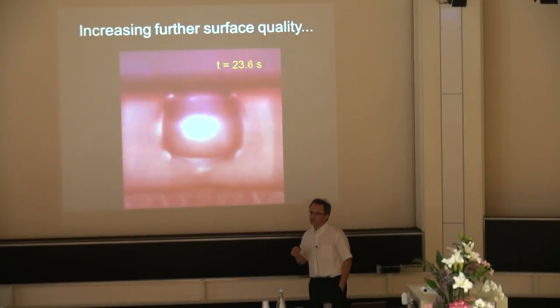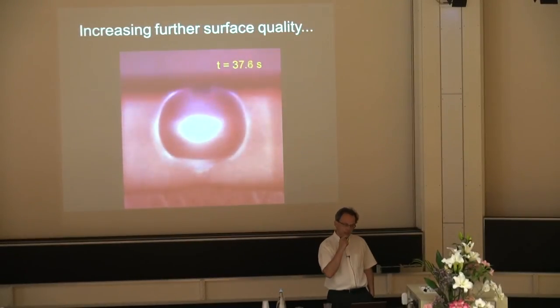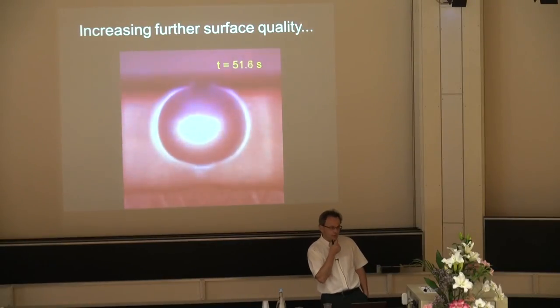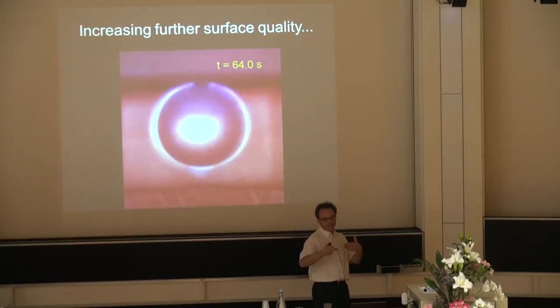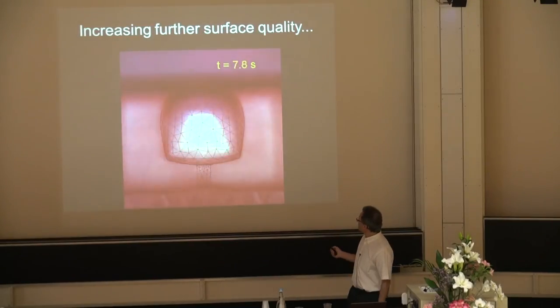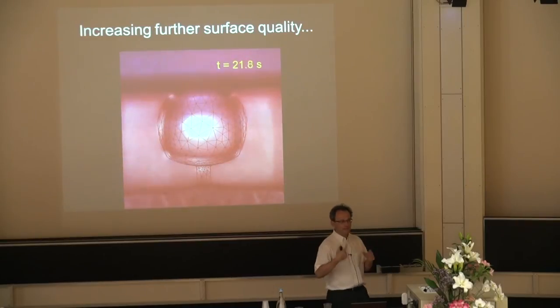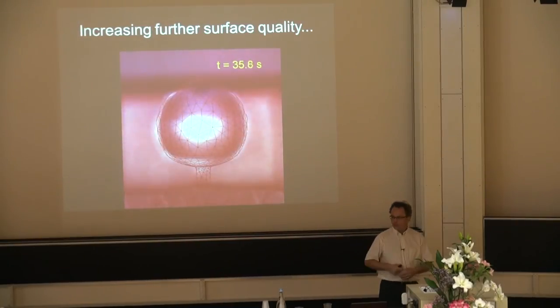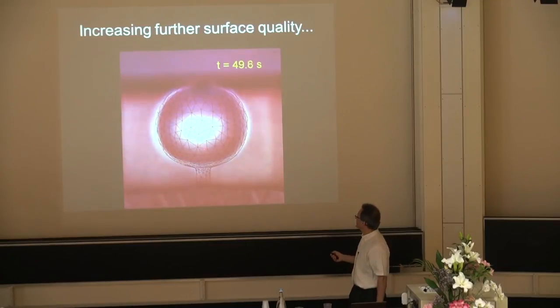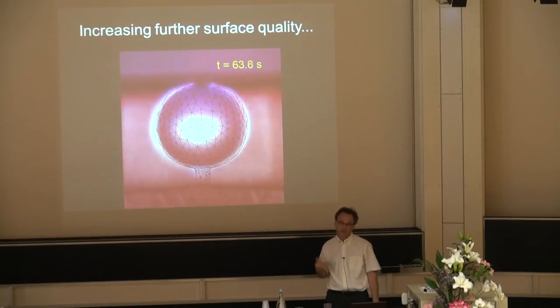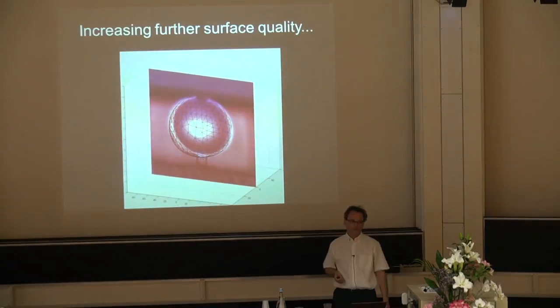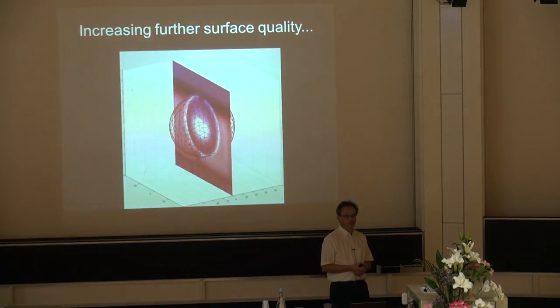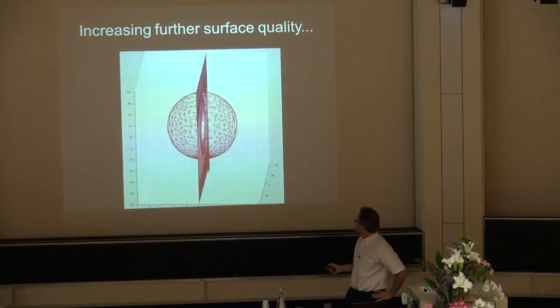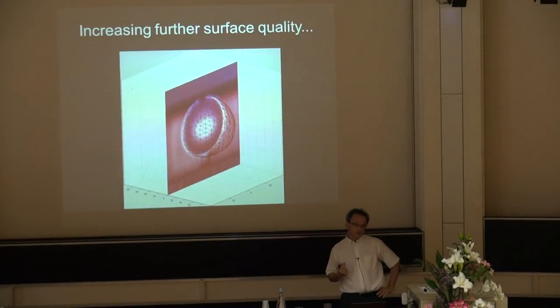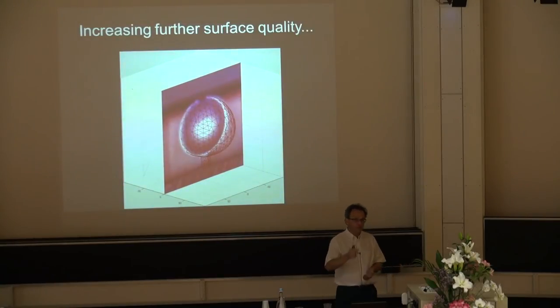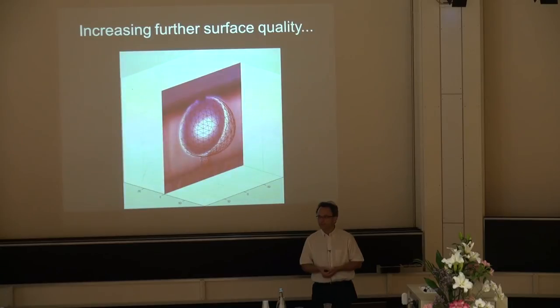Now, here's a trick. Suppose I start from a cube, and now I fire another laser. Here it's a CO2 laser, and I melt the glass, so I force it to melt. Now it's behaving a bit like a liquid. If I go high enough, of course, I have to go to 2000 degrees, then like a drop of liquid, by surface tension it will converge to the perfect sphere, because this is the minimum energy for the system when it's driven by surface tension. And then it's perfect because what is driving the shape is the physics and not whatever system I'm using to do that.